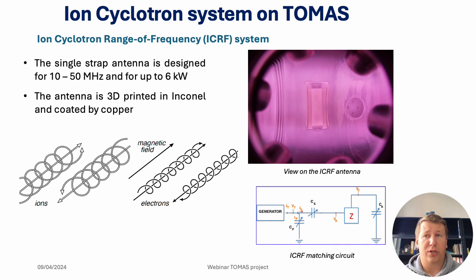Ion cyclotron wall conditioning uses fluxes of charge exchange neutrals created in plasma for wall cleaning. Ion cyclotron wall conditioning is based on the ion cyclotron resonance heating of plasma. In this case, the energy is transferred mainly to ions using the cyclotron resonance mechanism. However, this type of heating requires an antenna in the matching circuit to deliver the radio frequency power to the plasma. In the TOMAS device, we use the so-called ion cyclotron range of frequencies system, since with the low magnetic field we can only use the harmonic heating of the plasma.